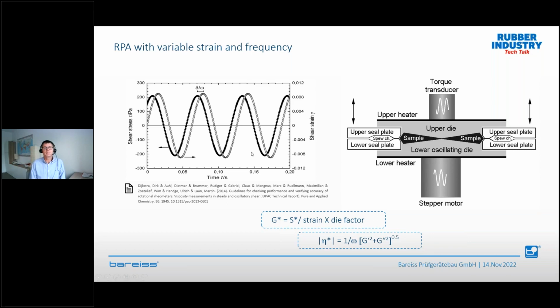And how do we calculate a shear modulus from this data? That is something I put here in this formulation. So we measure a torque value, which is called here S star. We divide it by our strain signal. This is what our motor is giving, for example, 0.5 degree of arc. And we multiply it with a die factor. This is because of our cone cavity. This is what you can read in every rheology book.